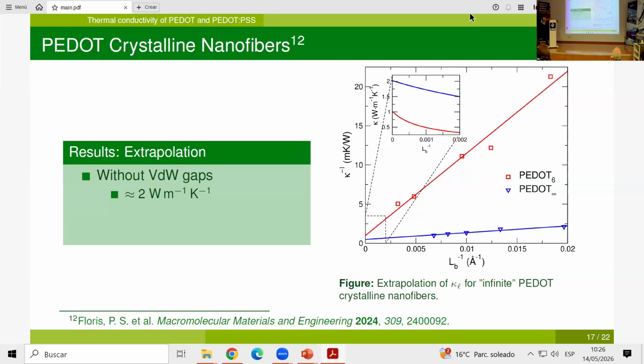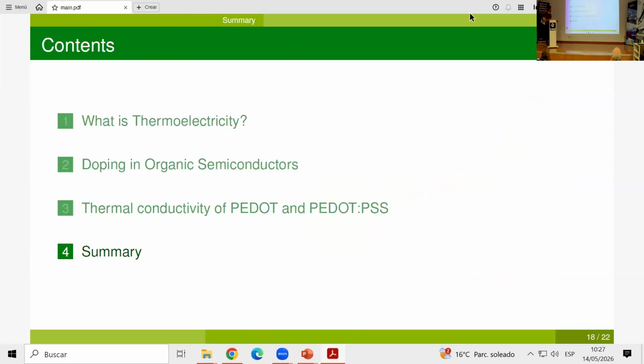We were also able to extrapolate the thermal conductivity for infinitely long chains without van der Waals gaps at around 2 watts per meter Kelvin, whereas when we consider the van der Waals gaps, it goes down to just 1 for an infinitely long nanofiber made of PEDOT chains of 6 monomers.